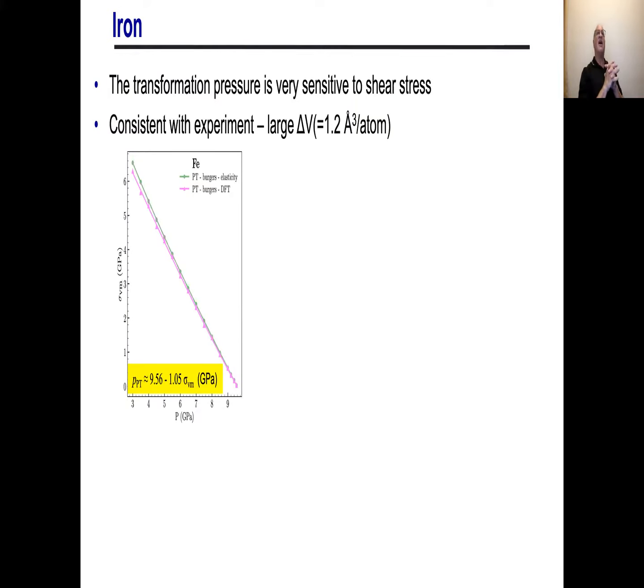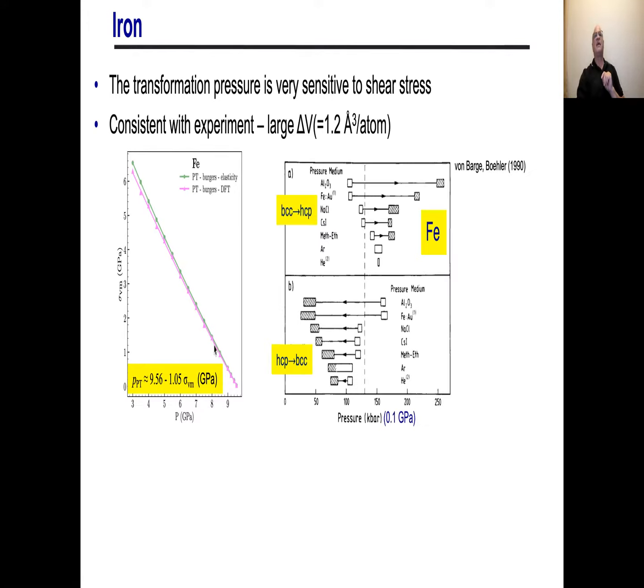Okay, so let's focus first on iron. The transformation pressure in iron is very sensitive to shear stress, as I talked about before. The difference in volume per atom in the two phases is about 1 cubic angstrom per atom between the BCC and the HCP phase at 0 pressure, quite large. And so that gives you this curve. So very strong pressure dependence. Now, if I go back and look at the data I showed you earlier on, as you go to higher and higher strength pressure media, that means I can have higher and higher shear stresses. And so as you go up in yield strength, you're going to go to a much larger range of shear stress you can get, and therefore a much larger range of transformation pressures, which is sort of consistent with this. The larger the shear stress you can put on, the more you can shift the pressure.